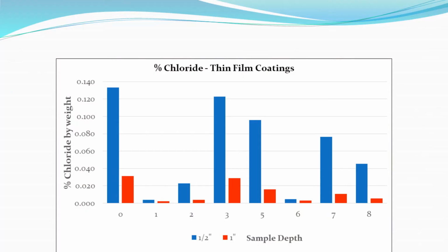Contrast that to the chloride, to the thin film coatings. There were 8 systems submitted. The zero system, what's labeled as zero, is the uncoated and ponded block. So this gives you your baseline. So the concrete itself, which the concrete mix design or matrix for the 2 studies were very similar.